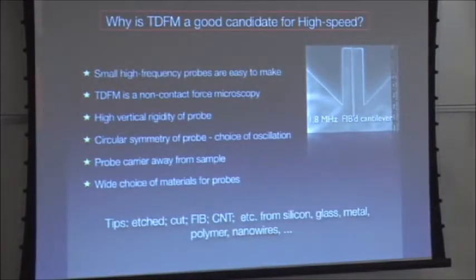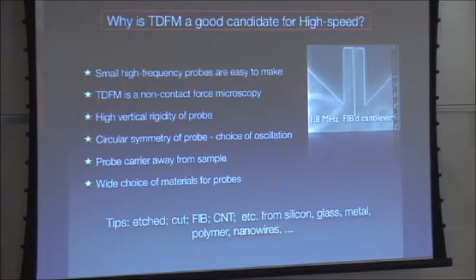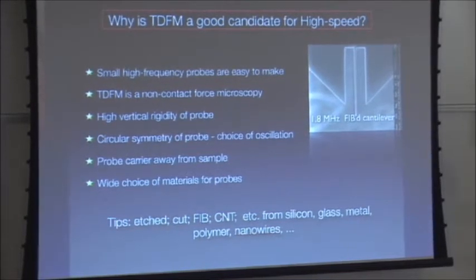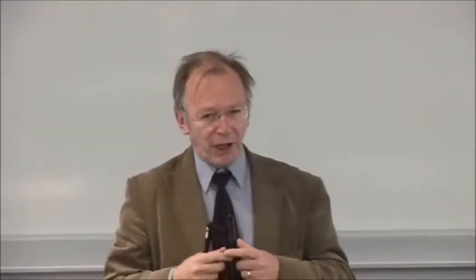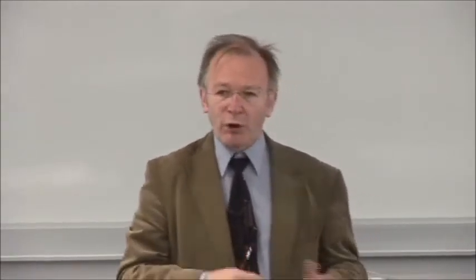Okay, so let's go faster. The way we're going faster in this case is very similar to what you can almost call the conventional high speed, where you just make everything on a shorter time scale. You just make your cantilever smaller with a higher resonant frequency, you just scan everything faster. You just change the time scale of conventional AFM. So we'll do the same with this. We make the cantilever smaller so it has a higher resonant frequency.